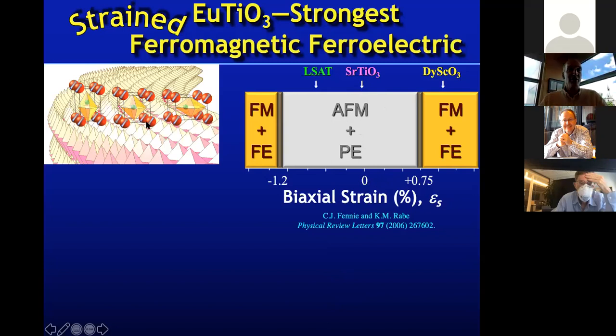So if we look over here to the cartoon, the europiums indeed all have 7 Bohr magnetons on them, but they're arranged in a G-type antiferromagnet. So the nearest neighbor europiums are all antiferromagnetically aligned with respect to each other. So overall, there is no net magnetization in europium titanate. Some of my colleagues would call europium titanate in its bulk form doubly boring. It's antiferromagnetic and paraelectric at the same time. But what Craig and Karin predicted was that landscape should change with either biaxial compression or biaxial tension. And the ground state should change to be simultaneously ferromagnetic and ferroelectric at the same time.